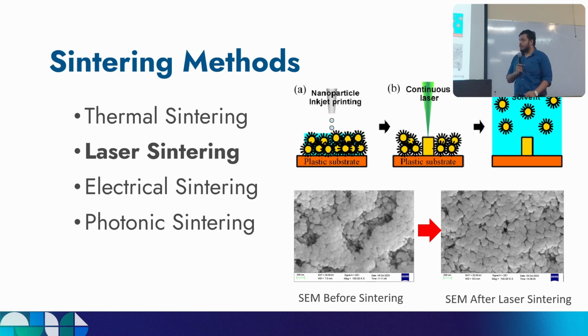So in order to overcome that drawback, scientists have found localized heating methods such as laser sintering, where we use a laser and focus it on the printed samples, and that causes localized heating, which results in the organic solvents being evaporated more quickly and more efficiently.